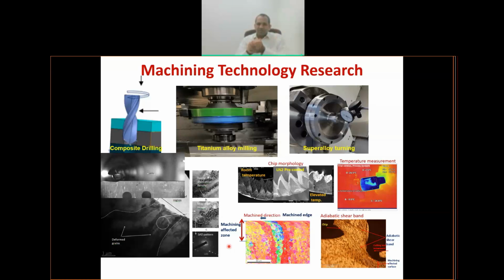When you machine a surface, the structure below it goes through very large, severe deformation. And that deformation is what we are able to see in this machining affected zone. You can also look at the shear band, which is on the right-hand side, bottom right. And that shear band could be looked at in transmission electron microscope, where you can start looking at dislocations and atomic structures. So you essentially can look at how the dislocation substructures and atoms are playing a role in the machining process, which finally results in a macro component of yours. So this is truly a very, very complex process.